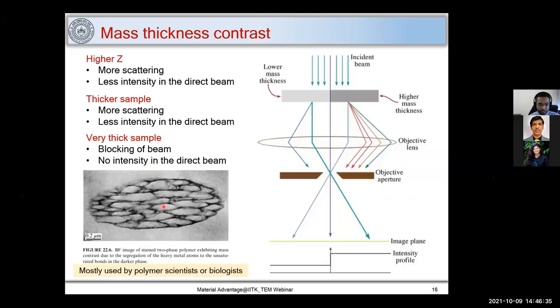So here in this case, it's an image from a book. You can see that these darker regions are showing a segregation of heavy metals in a polymer. And thus we get this kind of contrast. I can see a bright region here and a darker region here. The darker region is because these are high atomic number elements which are segregating in this place. So this kind of mass thickness contrast is mostly used by polymer scientists and biologists.